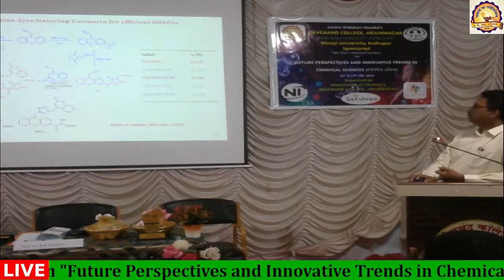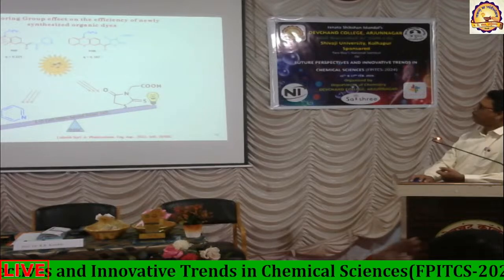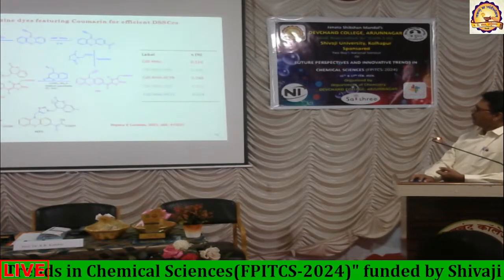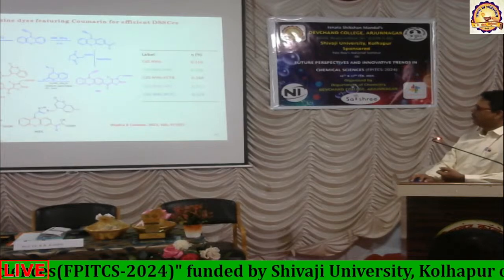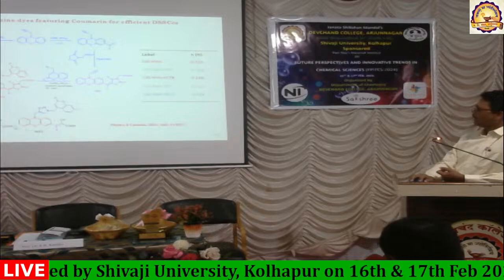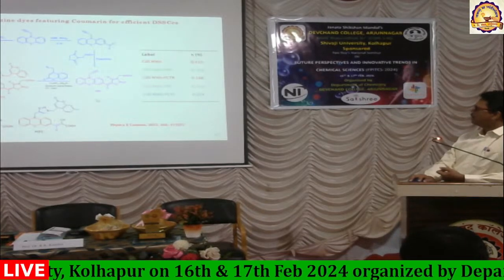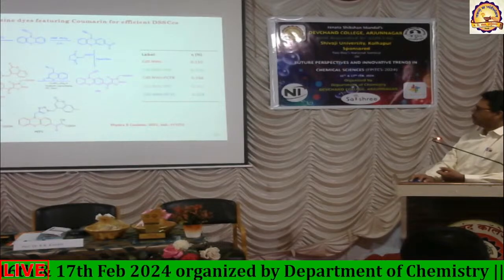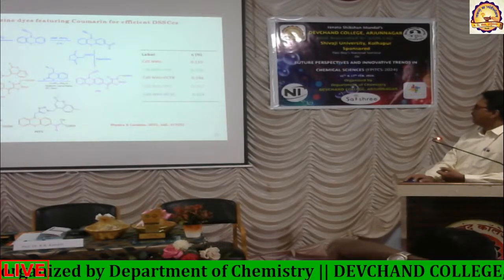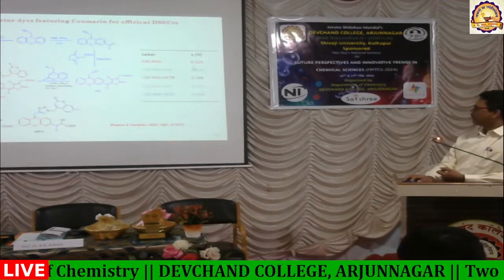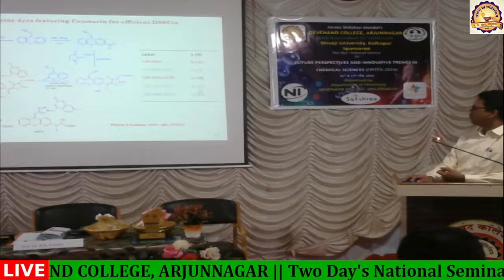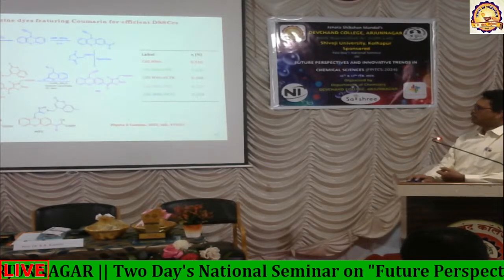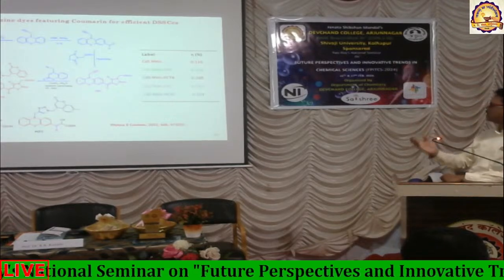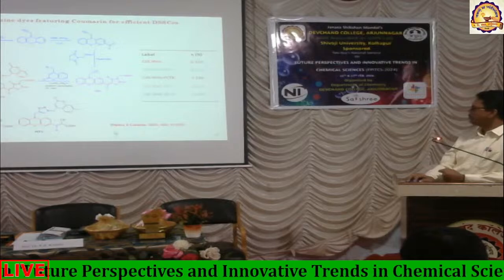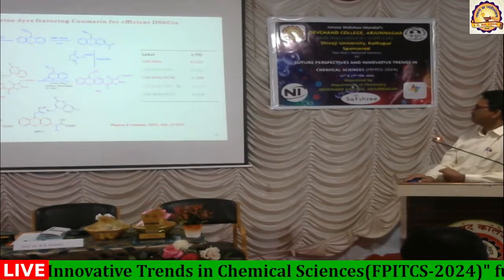Here we introduced a large alkyl group, and in this case we tried to introduce a heterocycle itself on this kind of molecule, with a cyanoacrylic acid as the linker. These are the 4 different molecules, PPR, PCTR, PPC and PCTC, which were used as dyes, and we tried to get their efficiency. The efficiency was almost double or tripled in these cases. The power conversion efficiency of these dye-sensitized solar cells was found to be higher, and this was published in a journal.